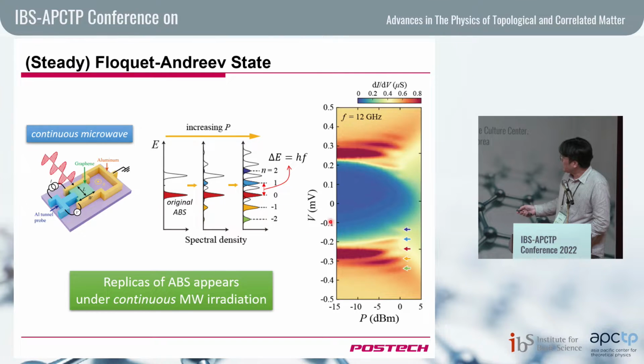This is experimental data. When the power is small enough, you will have only one pair of Andreev bound states, as you saw previously, and then we increase the power. Of course, the frequency was fixed at 12 gigahertz. hf corresponds to 50 micro eV. Okay? So as power increases, the original Andreev bound state peak decreases as the spectral density decreases, but the side peak appears here and also here, and if you have a good eye, maybe here, maybe not.